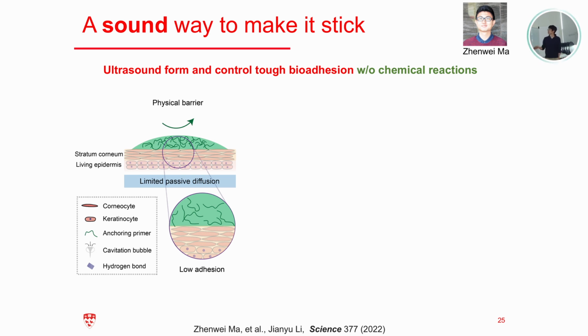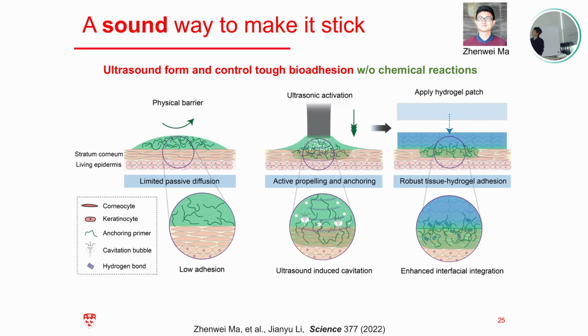Okay, so before we show you the detailed results, here is the big picture of our strategy. Essentially, as I said, we use ultrasound to induce cavitation inside the adhesive solution, for which we use the hydrogel as a model system, and it can increase the permeability of the tissue substrate. If you consider the skin, you have a very dense stratum corneum layer in the epidermis, which is very difficult for typical polymer materials to get over. But with the help of ultrasound creating microcavitation, we can propel this adhesive polymer like a nail or staple to get through at the molecular level, and by further applying this adhesive patch, we can form a strong adhesion between the hydrogel and the tissue.